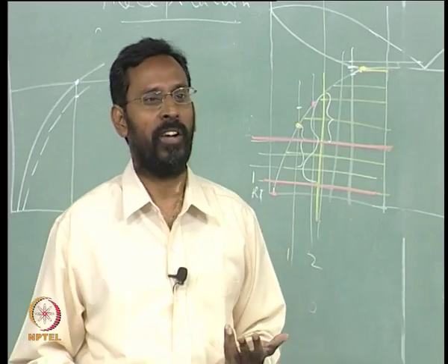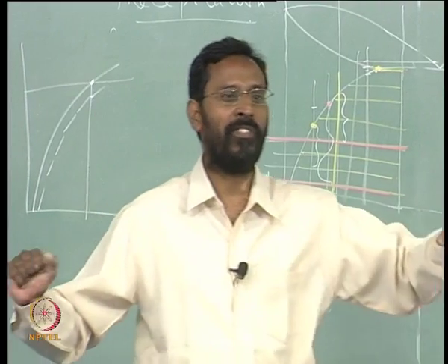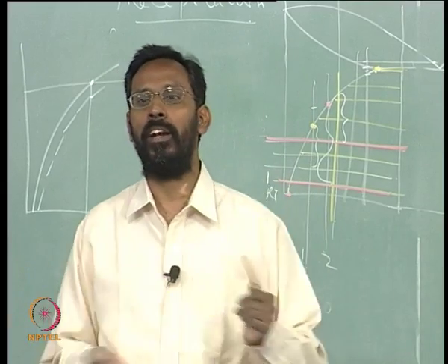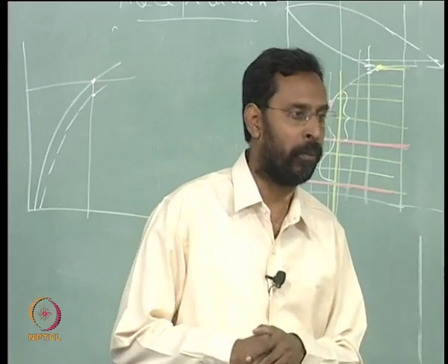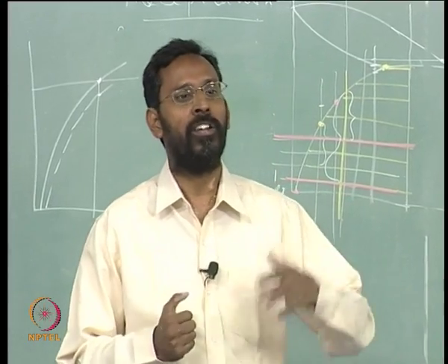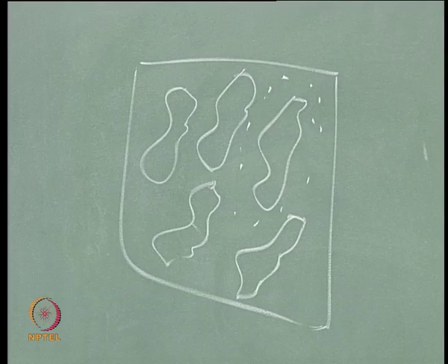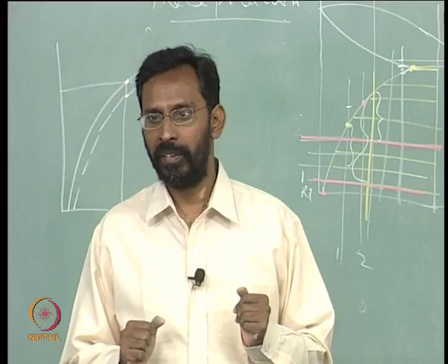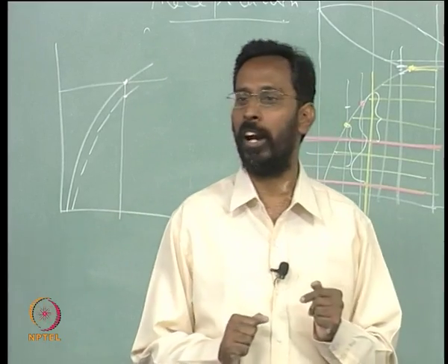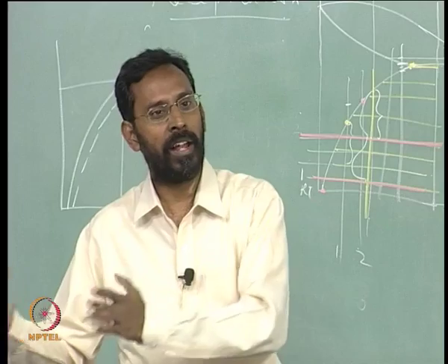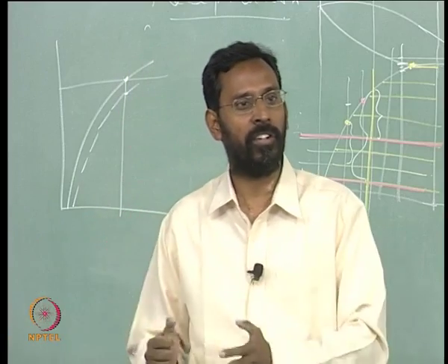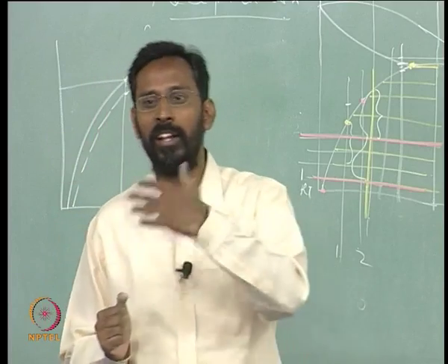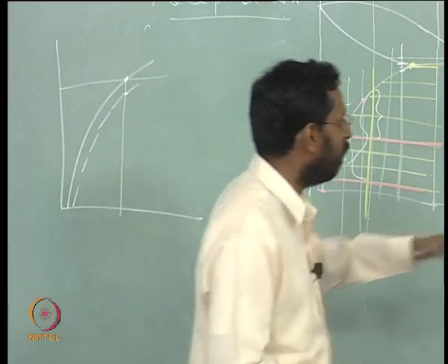is what nucleates first. That is where people always say FCC kind of phases are easier to nucleate than orthorhombic kind of phases, and that too it is an intermetallic compound. So intermetallic compound nucleation is more difficult than a solid solution nucleating, because in a solid solution it is all random, chemically it is random, structurally not random, but chemically it is random. Whereas in an intermetallic compound you have an ordered structure, so you have fixed positions for the copper and aluminum. So that is why it is more difficult to nucleate. Anyway, those are the issues.